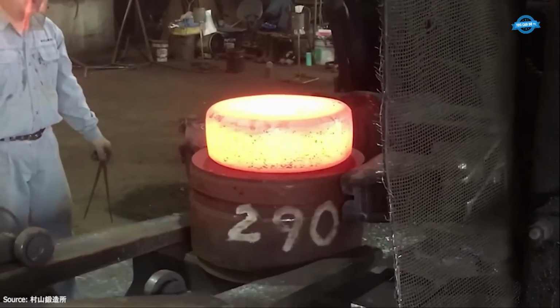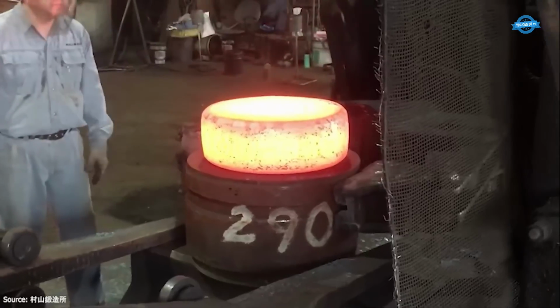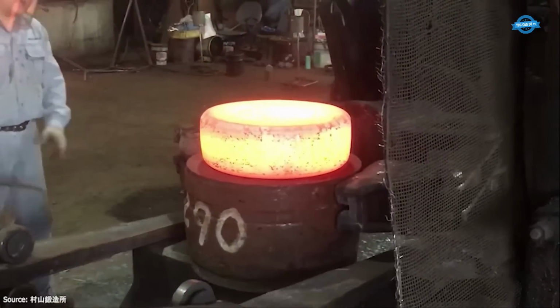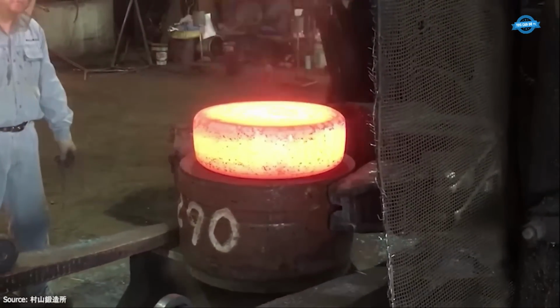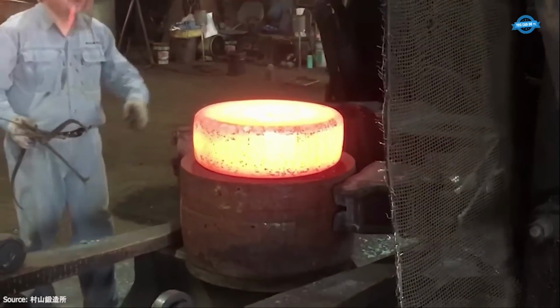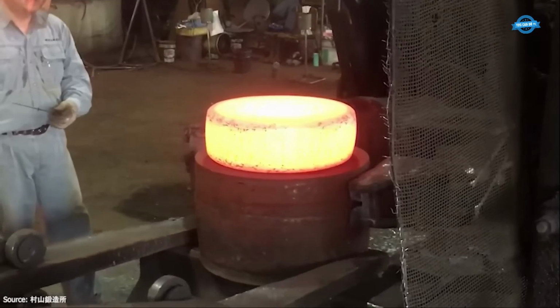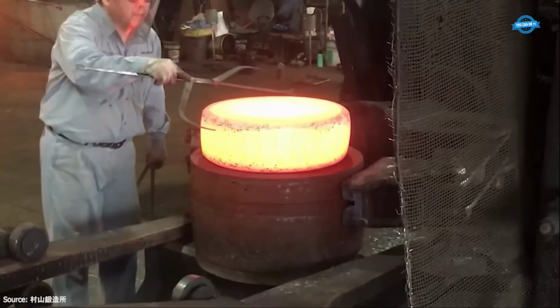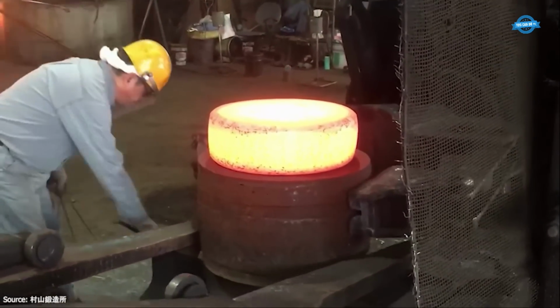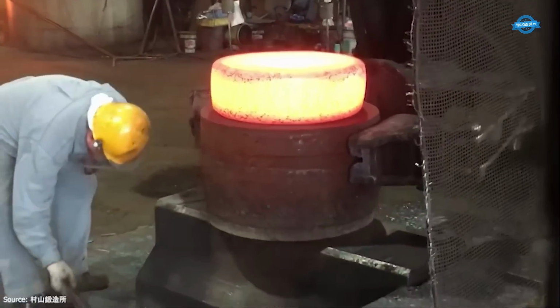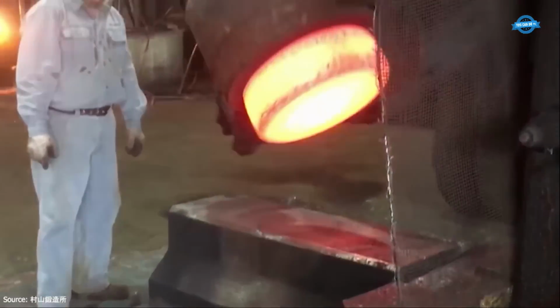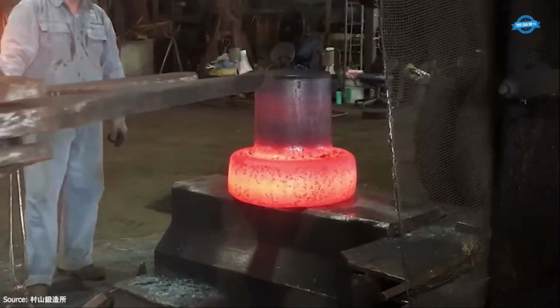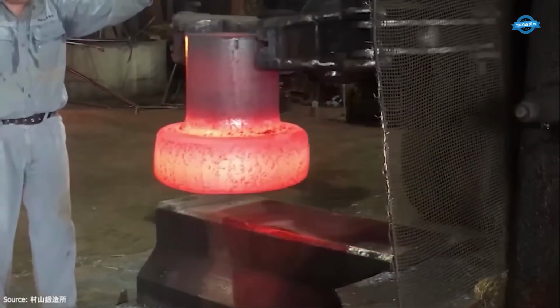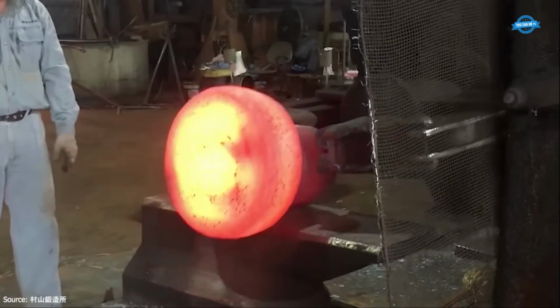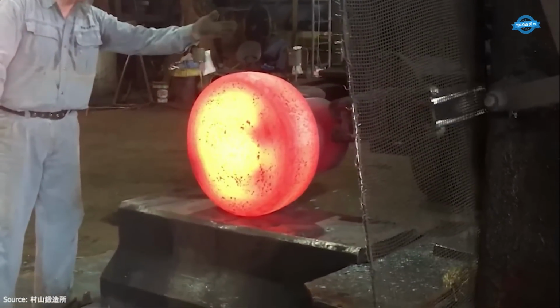The forging enters the critical adjustment phase. The piece's dimensions are refined. Operators monitor both the diameter and height, ensuring that tolerances are met precisely. In Murayama's operations, dimensional tolerances for large couplings are often held within plus or minus 1 millimeter. Multiple measurements are taken during this phase using calipers and template gauges. If needed, slight reheating in the furnace may be performed to maintain optimal forging temperature during the final adjustments.